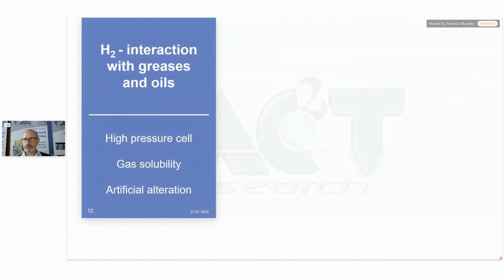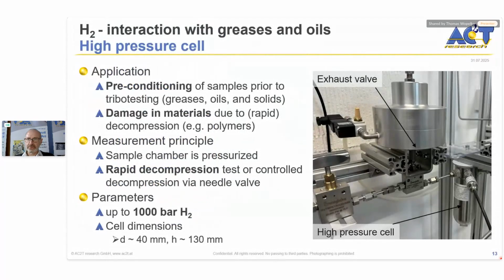So what is important is that you also investigate the H2 interaction with greases and oils. So we also have several methods to do this. First thing is actually a quite simple method. You just store the samples you want to investigate in a high pressure cell. This can be solid samples, greases or oils, with the goal to influence or damage the investigated samples.